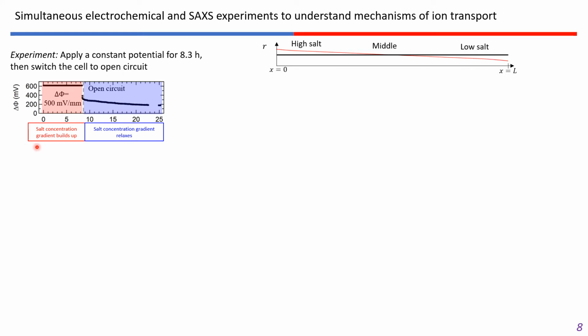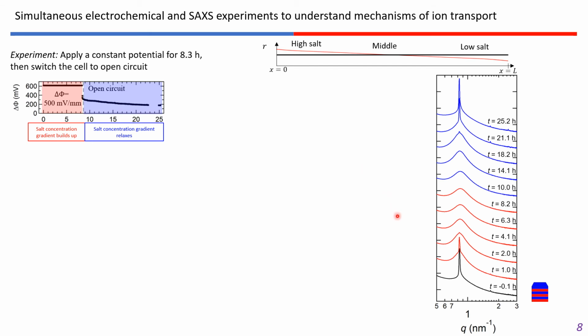Here we applied 500 millivolts per millimeter for 8.3 hours, at which time the salt concentration gradients will build up, shown in red. After that time, we set the current to 0, switching the cell to open circuit, and those curves will be shown in blue as the salt concentration gradient relaxes. So we can look at the 1D profiles from 3 regions of the cell. Starting at the bottom, at early times, the morphology is initially lamellar, indicated by the sharp scattering peak in the black curve. But as the polarization continues, we see this sharp scattering peak give way to a broad scattering peak indicative of the disordered morphology.